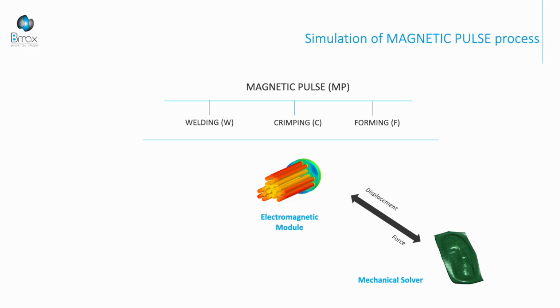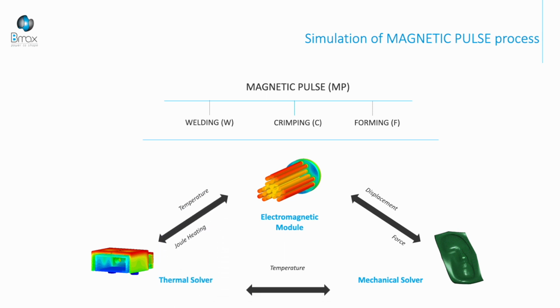In the metallic part, when we have a current induced, for example, we create heating. And we have to perform a coupling between the thermal solver and the electromagnetic module, for example, to update the electrical conductivity. Because when the temperature increases, we have a decrease of the Lorentz force and of the efficiency of the process. That's why we perform these three couplings between the three solvers.